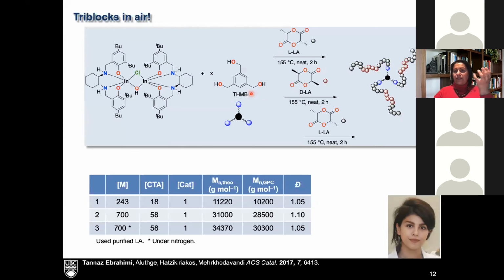And in air, and we're talking about Vancouver air, so Vancouver is quite humid. And under these conditions, we can add unpurified lactide, different enantiomers of unpurified lactide. And what we could see was really beautiful polymerization, forming very well behaved polymers, with basically the same theoretical and observed molecular weights. And if you compare that to the purified system, you see basically the same thing.